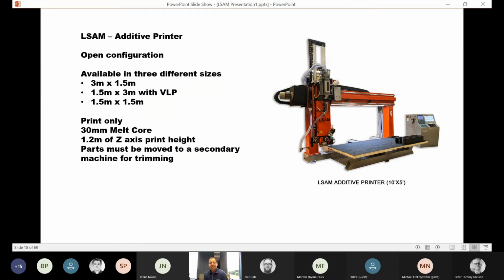The LSAM additive printer is a print-only machine with a 30 millimeter melt core. The print height is a little bit shorter on the Z. It's 1.2 meter. And then after the part has been printed and cooled, it must be moved to a secondary machine for trimming.